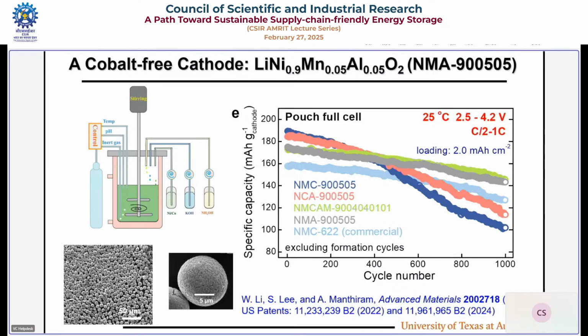NMA: 90% nickel, 5% manganese, 5% aluminum. That cycles in a full cell, 1000 cycles, graphite anode, pouch cell, as good as any cobalt-containing material. So in my opinion, cobalt is not necessary in the layered oxide. Of course, you have to do co-precipitation properly. I have a startup in Houston working on making these cobalt-free cathodes. So, cobalt eliminated.